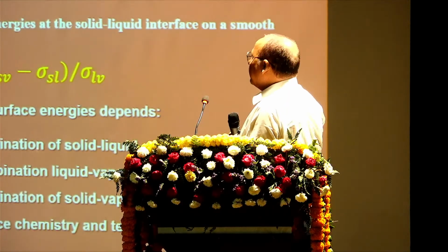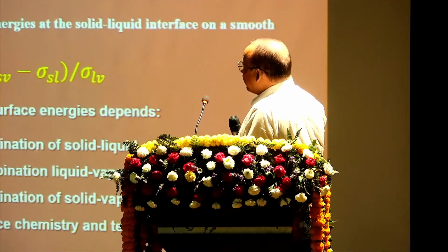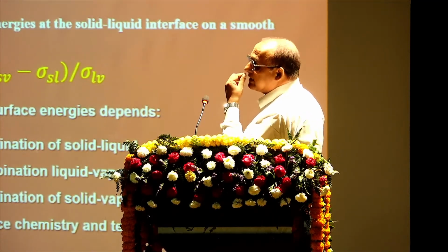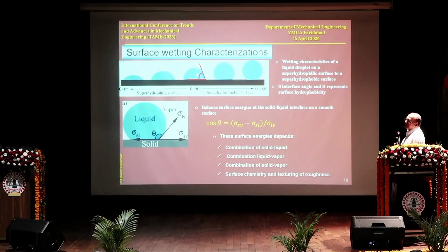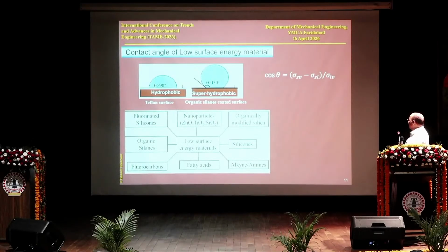The contact angle we can find out by the Young equation. It is the balance of three surface energies: the solid-liquid interface energy, the liquid-vapor interface energy, and the solid-vapor interface energy. You can see clearly in these pictures, the three-energy balance gives cos theta. When theta is less than 90, we say hydrophilic surface, and for super hydrophilic surfaces the contact angle is less than 20 degrees. A super hydrophobic surface has a contact angle of more than 150 degrees. Next slide.